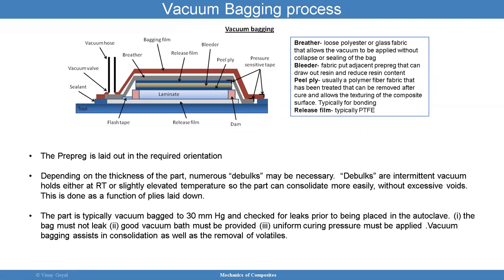This is done as a function of plies laid down. The part is typically vacuum bagged at 30 inches Hg and checked for leaks prior to being placed in the autoclave. So you have to make sure that there are no leaks in your vacuum bagging procedure. The bag must not leak. A good vacuum must be provided.